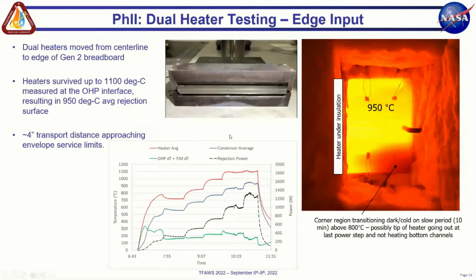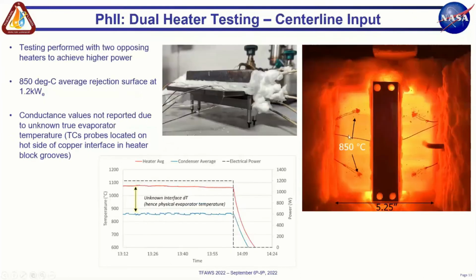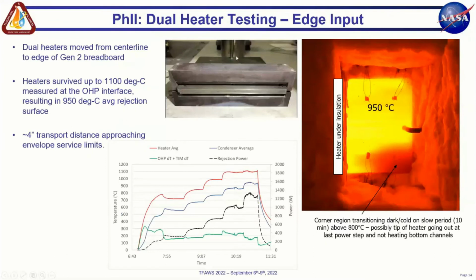Okay, so what's next? So we had shown the center heating, but the transport distance is only on the order of 2 inches. So the full width of the part here is 5 1/4. So we shifted the heater to the edge of the part to try to drive that heat instead of 2.5, more like 5 inches across the part, to explore a larger, longer transport distance. And it worked well. And on this test, we got, air quotes, lucky. The cartridge heaters survived with the actual heater blocks running on the order of 1100 degrees C for this testing, and we're able to get the OHP condenser up to 950C.